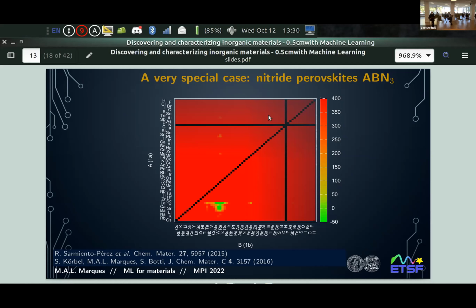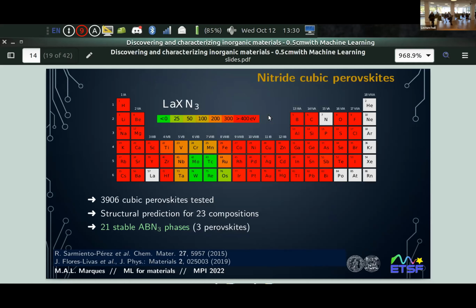So we went a little bit further. I have a zoom here for when A is lanthanum. And it becomes quite clear. Maybe you can have lanthanum molybdenum nitride, lanthanum technetium nitride, maybe not a very interesting compound. And with tungsten and rhenium and maybe osmium, those are the most likely ones, okay? We did a little bit more calculations. We found out that around 23 compositions were promising, but most of them, in the end, would decompose or distort to something that was not a perovskite. So our conclusion is that only 3 compositions could yield a nitride perovskite.